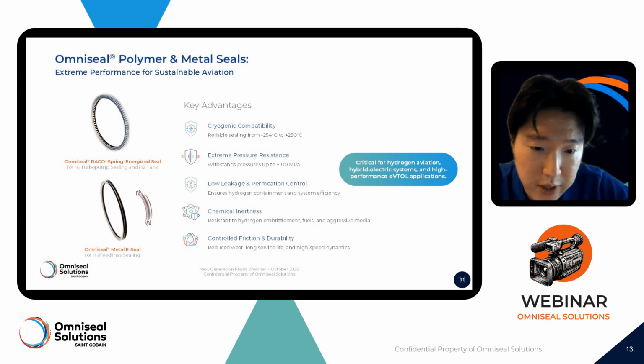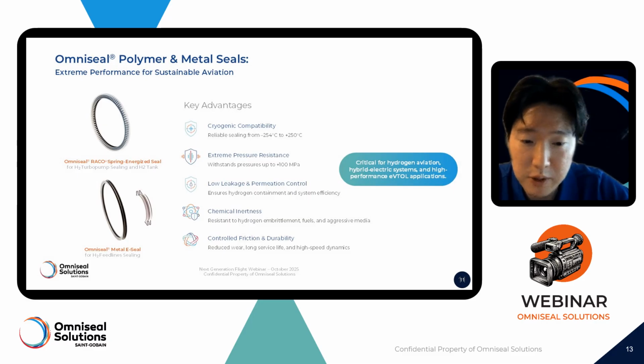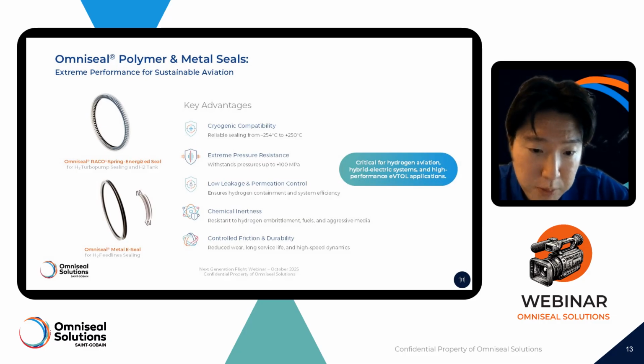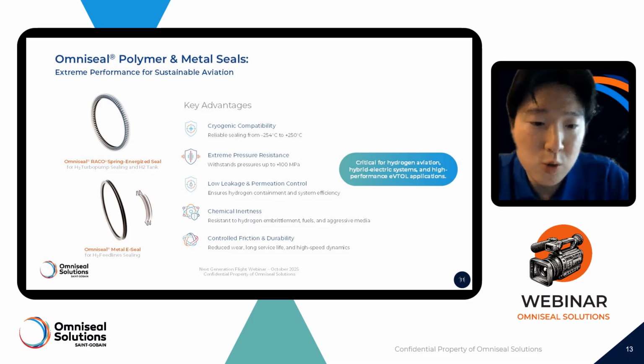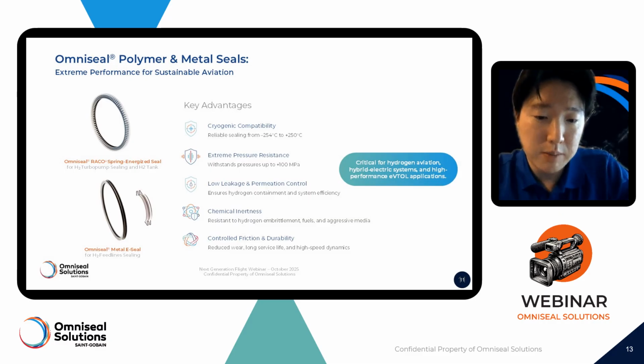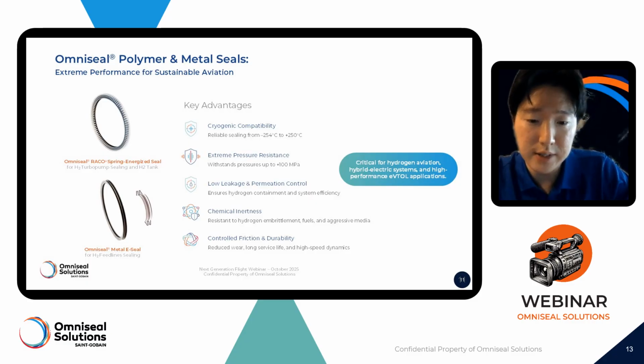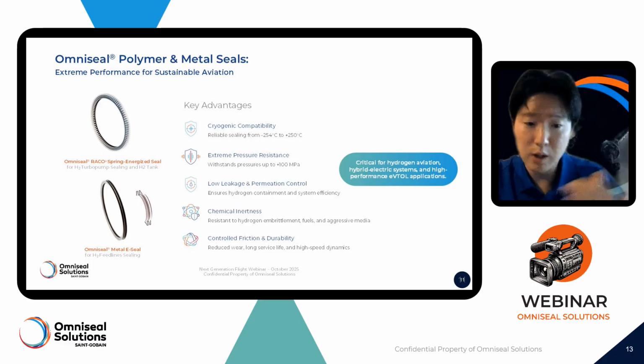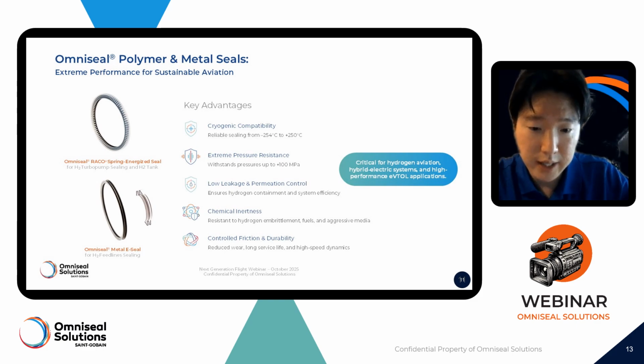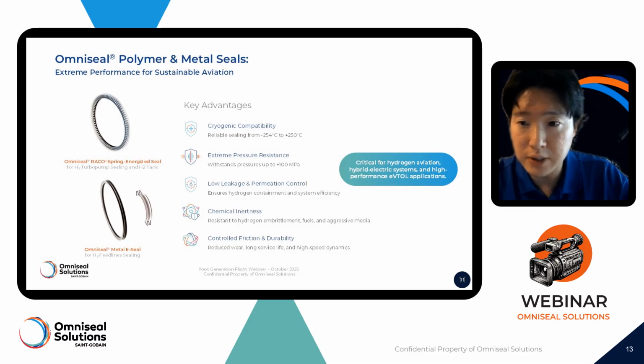But the key advantage here is certainly, first and foremost, cryogenic compatibility. So reliable sealing from the cryogenic temperature of negative 254 Celsius to 250 C or above. Extreme pressure resistance up to 100 megapascal, low leakage and permeation control. So these are proven solutions in the field already, ensuring hydrogen containment and system efficiency. They're also resistant to hydrogen embrittlement, fuels, and aggressive media, right? So this chemical compatibility is certainly a